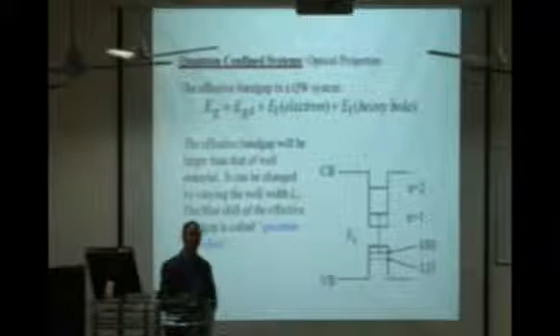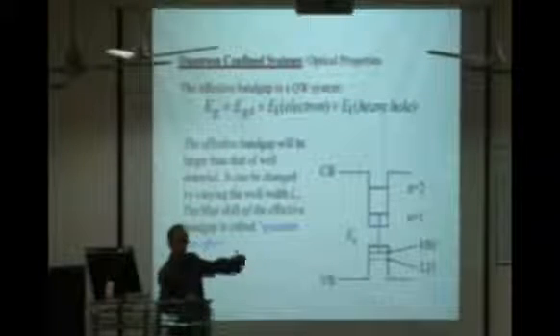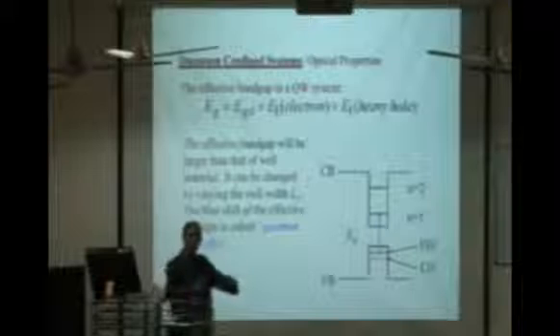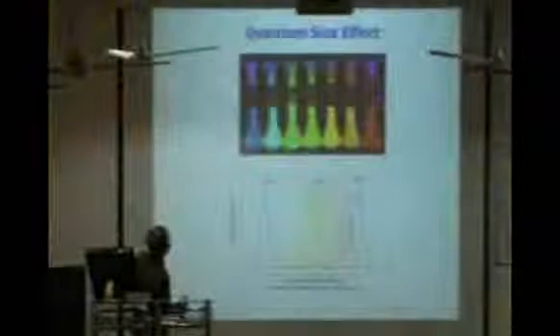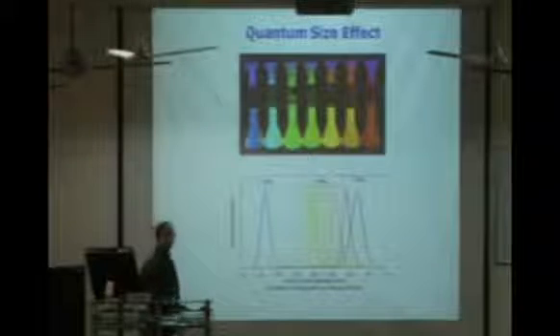That is actually one of the biggest uses of quantum mechanics: to make quantum well lasers of any wavelength. Because naturally you don't have semiconductors of all wavelengths. Suppose for fiber optic communications, only one or two wavelengths actually pass through the fiber optics with very, very little absorption. It's about 1.54 micron. But unfortunately, you don't have any semiconductor which gives an emission of 1.54 micron. So you have to alloy different semiconductors with different sizes of this quantum well so that you can get exactly the same band gap. So this quantum size effect is very important for many other applications, for semiconductor doped glass.